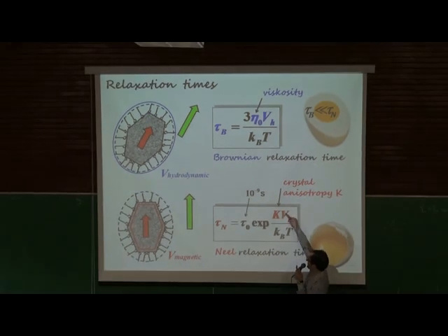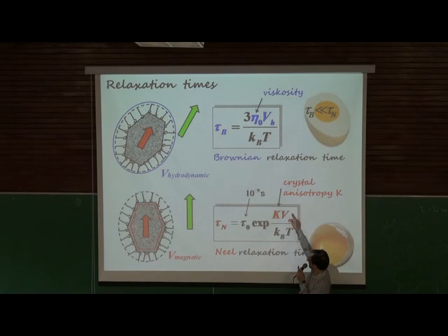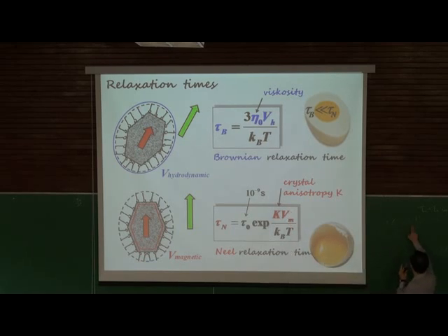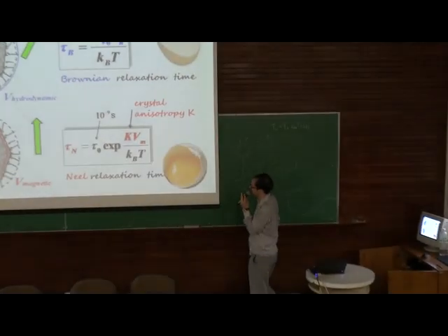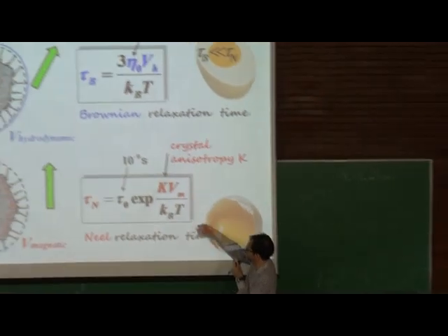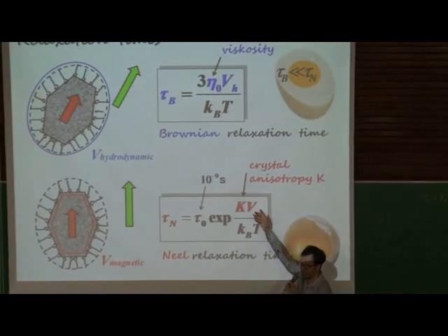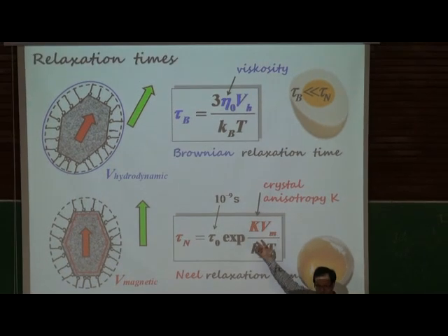So the size is really very sensitive. And it can be that these particles are already so small that the Neel relaxation time is dominant, so they are not Neel blocked.